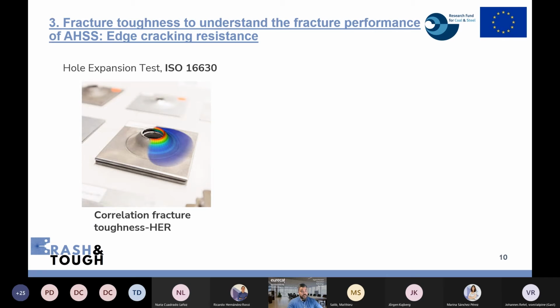We know that edge cracking resistance is usually quantified by means of the hole expansion test and the hole expansion ratio, which is a measure of the stretch flangeability of the steels. It is well established and a simple method, but the reliability of these tests is often put into question, because there is large variability. It is not a material property, and it depends on many variables, like the punch to die clearance, the alignment of the tool, the operator, the system used for crack initiation and detection, and so on. That's why researchers have dedicated several efforts to find mechanical properties that can define this stretch flangeability in a more objective way.